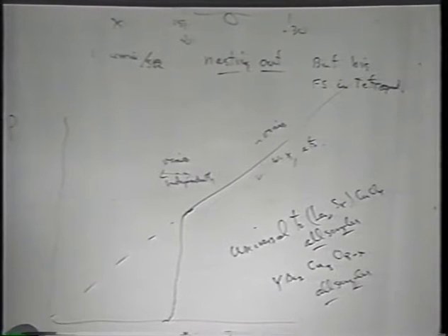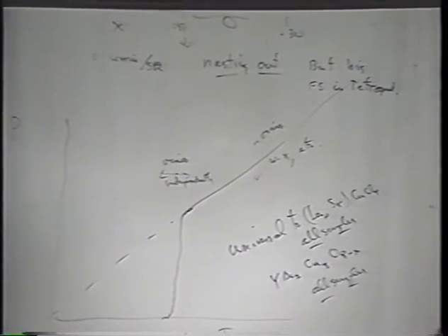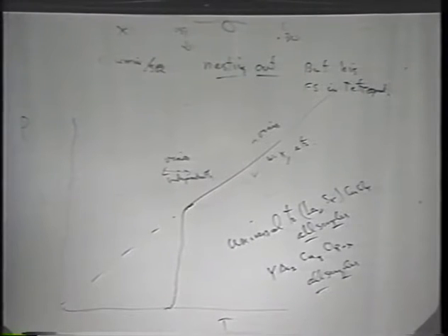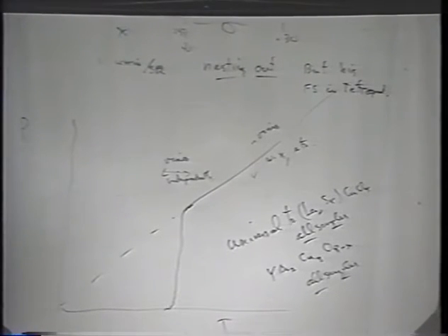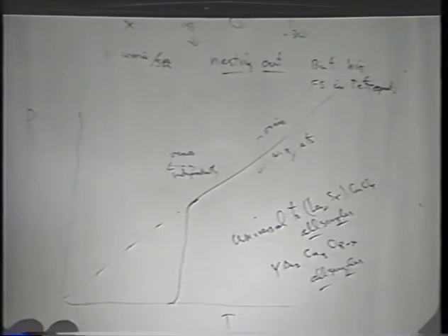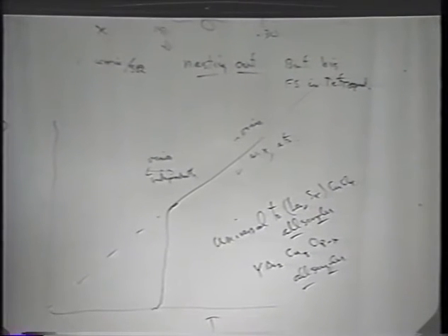The peculiar resistance that I referred to is this strange fact that when you get a good sample of any of these materials, the resistance seems to extrapolate to zero. As I was looking at the data from various other people, I wasn't sure what this power law was, but I was always sure that it extrapolated to zero when I got a good sample. And that's a very strange thing. Think about that. What has a zero resistance at t equals 0 when it is so darned impure? It is extremely impure. It is extremely random.